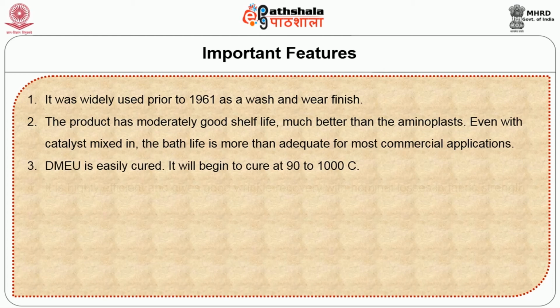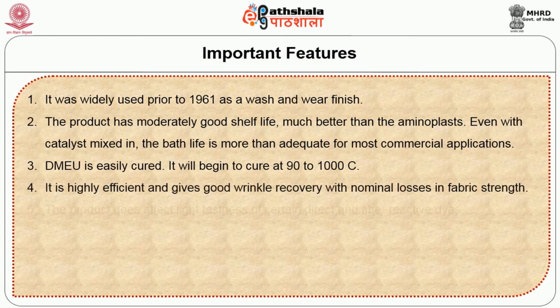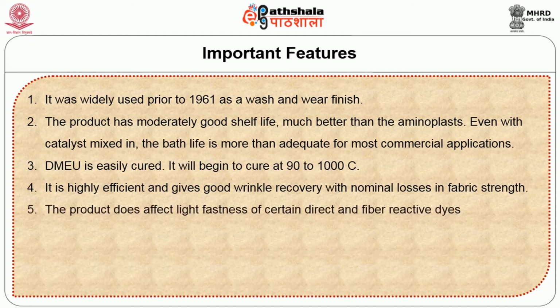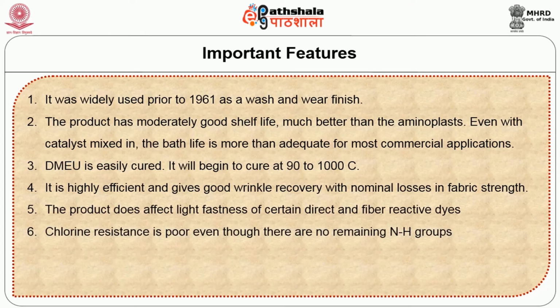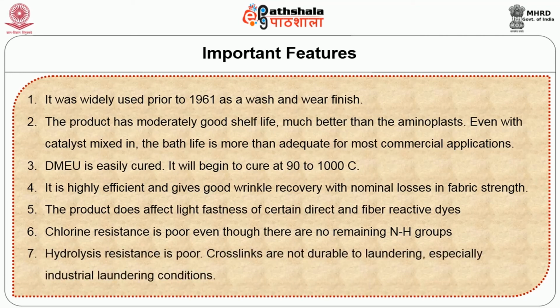It will begin to cure at 90 to 100 degrees Celsius. It is highly efficient and gives good wrinkle recovery with nominal losses in fabric strength. The product does affect lightfastness of certain direct and reactive dyed material. Chlorine resistance is poor even though there are no remaining NH groups. Hydrolysis resistance is poor. Crosslinks are not durable to laundering, especially industrial laundering conditions.